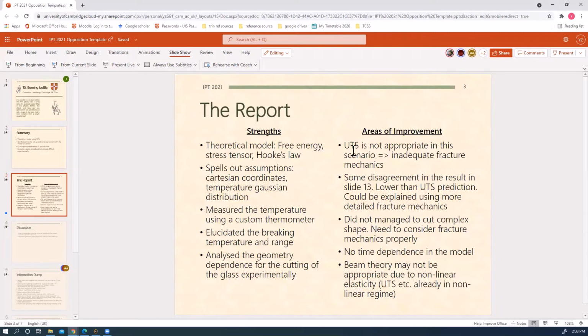And in contrast, in glass, when we're talking about the creation of new fracture surface, the energy required is actually very little. So a crack can propagate very easily if there is an existing crack tip. So in this case, the ultimate tensile stress is not going to be very well defined because it's going to be extremely dependent on the surface condition.